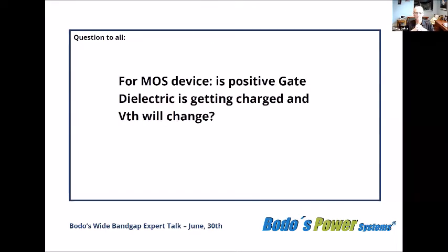Thank you, Alex. A question to all. For MOS devices, is the positive gate dielectric getting charged and will VTH change? If I may, I think there's some confusion on that. In most devices, and I can speak to devices at EPC and at Navitas, there is no gate dielectric. It's actually a p-GaN gate. It's a positively charged gallium nitride, which is not a dielectric.